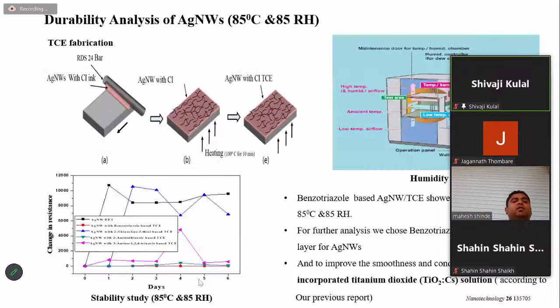To check which corrosion inhibitor is good, we coated the silver nanowire on the substrate with the corrosion inhibitor. To check its corrosion and stability, we put this electrode in the humidity chamber. The temperature of the humidity chamber is 85 degrees Celsius and the humidity is 85 RH. So it's a very harsh condition. We kept it like this for 6 days, and in 6 days we found that benzotriazole is the best material which can protect the silver nanowire